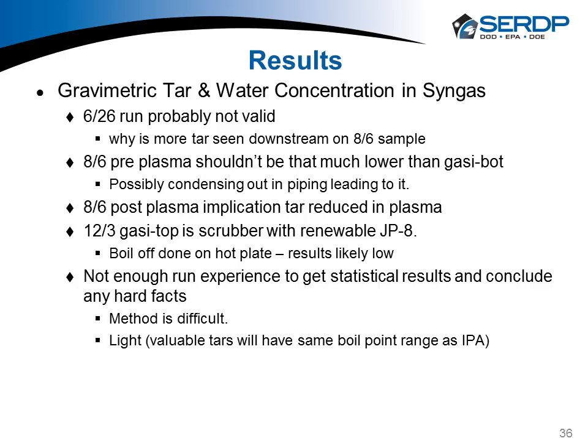Conclusions from that, again, the 626 run is probably not valid. The 86 run, the plasma shouldn't be that much lower than the gasifier at the bottom, and it could be a condensation problem. I didn't really talk about it, but we had preheaters or heat tracing throughout the system to keep the tars from condensing, but some of the samples, when we opened them up, we did see liquid tar, which says we weren't keeping it all in the gas phase.